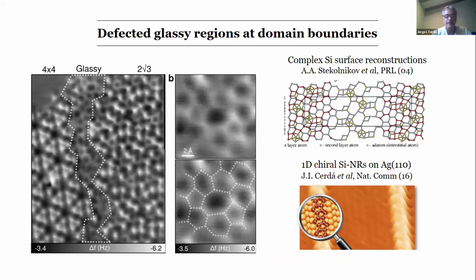Anyway, I concentrate now on the glassy regions, which appear at boundaries between two phases, the 4x4 and the square root 3. These are a kind of distorted region, and when you make a blow up on them, what you see is a kind of distorted silicene, highly distorted. It's very similar to what happens in many carbon systems.